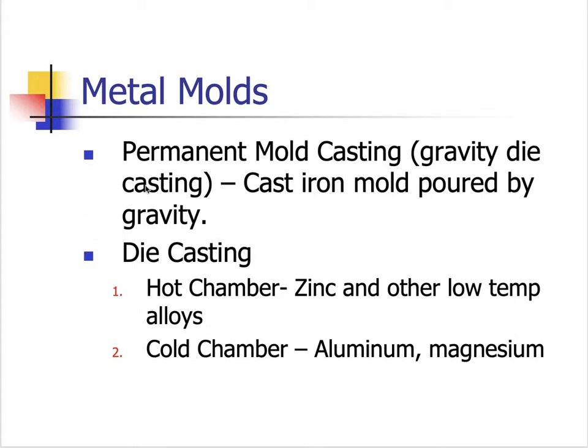Okay, so permanent mold or gravity die casting, essentially usually a cast iron mold, but it can be other materials, steel or something. And you pour aluminum or some other lower temperature melting alloy into it, brass, and you can use that die over and over again. The thing you do have to watch out for is it does get really hot, so it needs to be cooled either by water or by air, usually by air. And you can make a lot of castings, but remember that the cycle time on this is completely dependent on how fast you can suck the heat out of the casting.